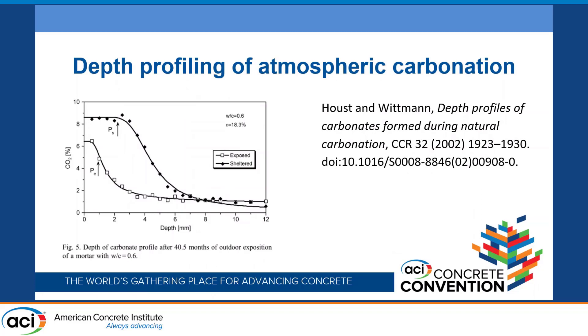When talking about durability questions and atmospheric carbonation of concrete in service, you could do profiling. The same way you would do chloride diffusion profiles, you can do the same thing with carbonate diffusion — taking slices of your sample to get a depth profile from the exposed surface into the depth of the sample, and come up with some diffusion information for CO2. You see this as part of the GCCA strategies, where the sustainability of concrete is somewhat tied to the ability to perform CO2 uptake. A technique like this gives stronger confidence in that solution.